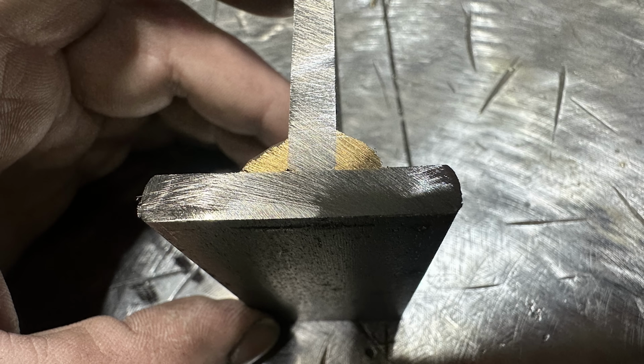And also, like I stated earlier, this does not work on capillary action where you're going to see braze material between that top and bottom plate. What you do is you keep the heat on the braze material, and then you keep feeding it with more wire, and you move along just like you're welding, and it will follow the heat to a certain extent. But you're not relying on heating an area ahead of where you're brazing and then feeding the filler on that hot material. You're basically keeping the heat on the braze, the bronze, and then you're just using it pretty much like welding. All right, I think you understand what we're looking at here.